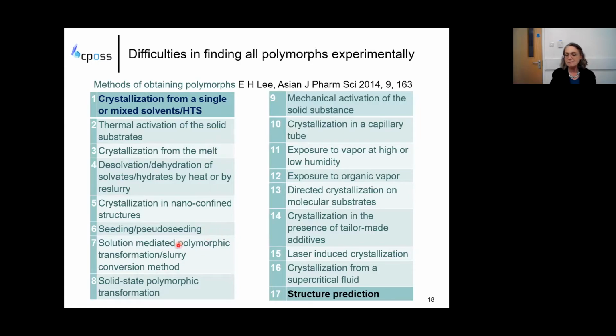things, including things that are based on having mechanical activation and energy to transform, or constraining your crystallization volume, or having impurities present, or having a laser, or using supercritical fluids, had all been found to find new polymorphs. Now, structure prediction can't cause anything to crystallize, except for the sociology that people look harder. And we can help characterize from less data, such as a powder.